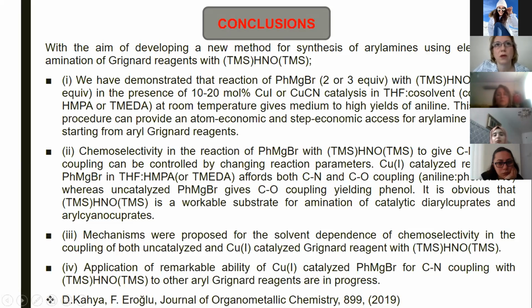This one-pot procedure can provide an atom economic and step economic access for aryl amine synthesis starting from aryl Grignard reagents. Second, chemoselectivity in the reaction of phenyl magnesium bromide with (TMS)HNO(TMS) to give carbon-nitrogen or carbon-oxygen coupling can be controlled by changing reaction parameters. Copper-1 catalyzed reaction of phenyl magnesium bromide in THF, HMPA, or TMEDA affords both carbon-nitrogen and carbon-oxygen coupling, whereas uncatalyzed phenyl magnesium bromide gives carbon-oxygen coupling, yielding phenol.